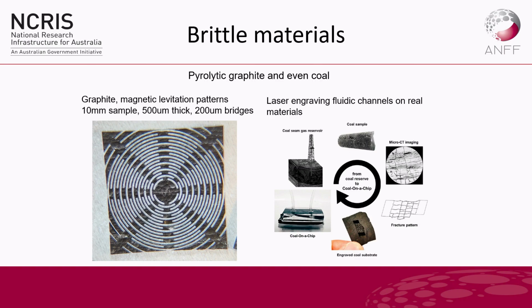Where it's really good is for machining very brittle materials. This is a piece of graphite, and you really don't want to take any sort of other tooling to graphite. It will just tend to fall apart on you. That piece that I'm showing there is about 1 centimetre in size. So all those little channels we've machined in it are quite fine, and the graphite stays together as long as you don't squeeze it too hard with a pair of tweezers.